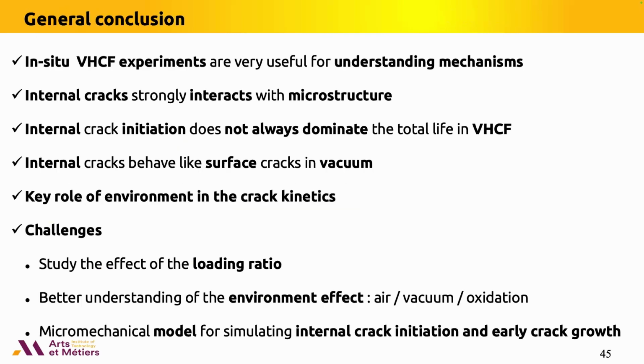As a general conclusion, this is my last slide. We can say that in situ very high cycle fatigue experiments are very useful in order to understand the mechanisms of internal cracks. There is a big interaction of the crack propagation inside the specimen with the microstructure, and there is not always a domination of the initiation process, but the crack propagation may dominate. The internal cracks behave like a surface crack in vacuum, and there is a key role, as I said, of the environment. For me, the challenges for the future are the following.